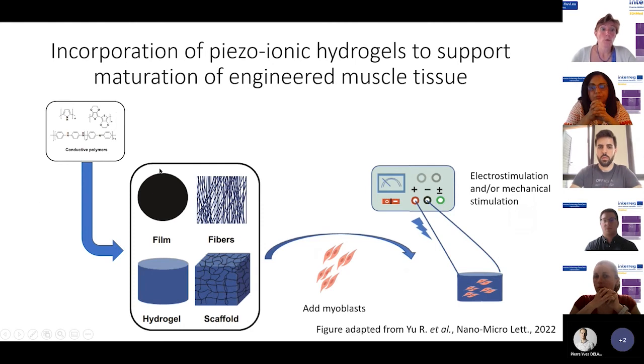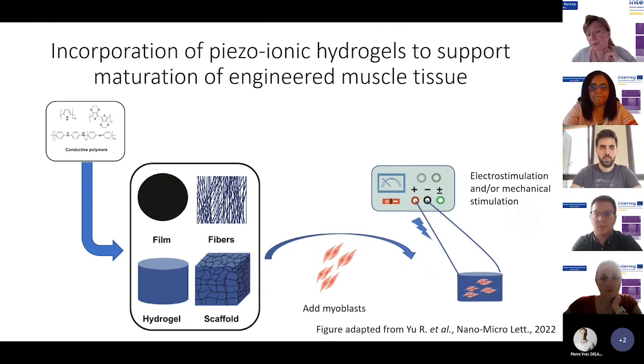also helping the muscle tissue to further mature. So what we do, we have the polymers and we put them either in a hydrogel or in a film layer, or we spin them into fibers, or we make a more robust or a more firm scaffold. But for muscle tissue applications, mostly a hydrogel is used. Then we add the myoblasts to the hydrogel, and then we can start to stimulate these preliminary muscle tissues in order to develop real muscle fibers and mature muscle fibers. We can do this via electrostimulation and or via mechanical stimulation. But the advantage of the piezo-ionic hydrogels is that if we apply mechanical stimulation, then at the same time there will also be an electrostimulation.